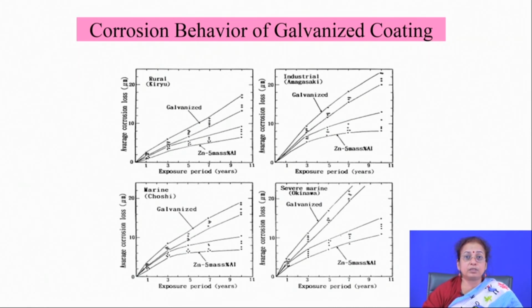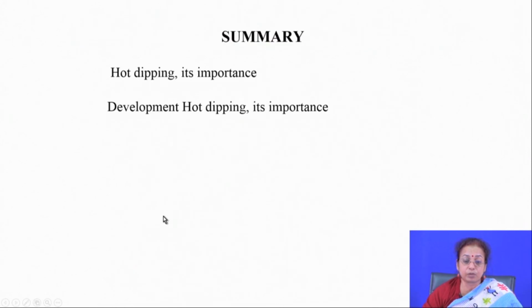Now, if you talk about the typical corrosion rate or lifetime of different coated products, you will find that by addition of aluminum, your average corrosion loss is reduced to a large extent. So, aluminum addition is very good because it not only reduces the possibility of intermetallic formation at the interface, but it also reduces the corrosion loss to a large extent. So, it is very important that you add aluminum and apply the galvan bath where your service environment is quite harsh in terms of environmental species, like a severe marine environment.